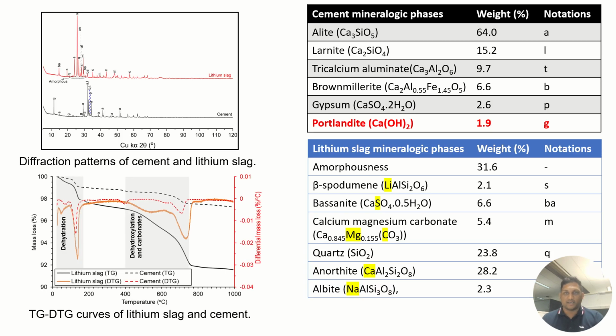The quantitative XRD of the cement showed 64% alite and 1.9% Portlandite, which can induce a pH of 13.7 in 100 ml DI water, while lithium slag retained 31.6% amorphousness at 22 to 29 degrees 2 theta in the diffraction pattern and mostly contains light metals, lithium, sodium, magnesium, and sulfur in the amorphous phase, other than calcium, aluminum, and silicon. Therefore, using lithium slag as a pozzolan may provide an amorphous intermediate hydration product compared to crystalline calcium silicate hydrate alone. This characteristic composition helps to induce long-term strength development in the pozzolan cement composite system.